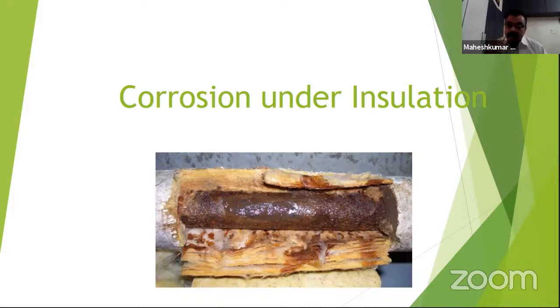This moisture is also carrying the salts with it. So I can directly say that instead of condensation, it's an electrolyte which is going to go down. Now, in such situations, it could be chlorine gas, it could be sulfur, which is going to dissolve into it. This dissolution is going to create an acidic media or an acidic electrolyte, which when heated at that particular temperature is going to make the situation very, very critical, because the acid and high temperature are both going to react with